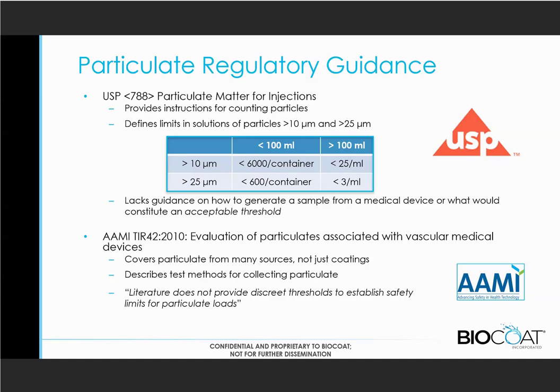And for containers, it will say that you should have less than 6,000 particles greater than 10 microns per container, or for 25 microns or above, less than 600 particles per container. The emphasis here is that it is per container. It is not designed for a medical device. And so translating what is a per container limit to a device can be a challenging issue. And the other part of that is it really lacks any guidance on how to generate the sample from a medical device, or, as said, what would constitute that acceptable threshold.